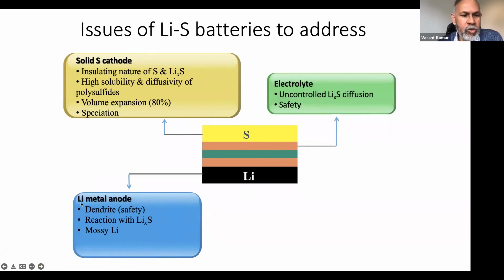Because this uses pure lithium metal, there is of course a tremendous learning curve in being able to use pure lithium. This battery produces only 2.1 volts. Also, there's a reaction that takes place between lithium metal and the polysulfide, which is soluble in the electrolyte, so it is continuously passivating the dendrite. However, at high charge rate, you might find the dendrite forms uncontrollably.